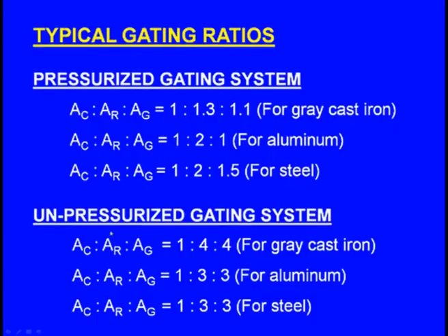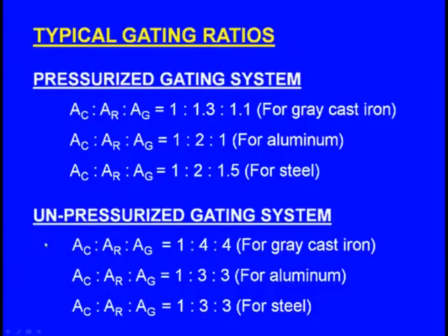Now, let us see the unpressurized gating system. Under this, again for the same important cast alloys, the gating ratios have been recommended after extensive experimentation. Now, for gray cast iron, AC:AR:AG is equal to 1:4:4. Similarly, for aluminum alloys,